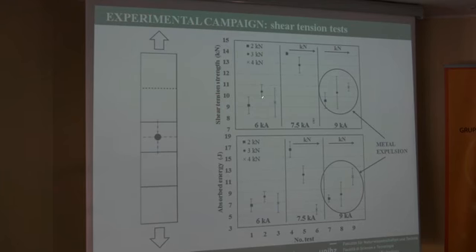In particular, you can see that there is an increase in the mechanical strength of these joints, considering also that coming from this position to this one, we have an increase in the nugget diameter that increases the mechanical strength. And then we have a reduction of the shear tension strength due to the fact that in these samples metal expulsion occurs, and so we have a loss of mechanical strength.